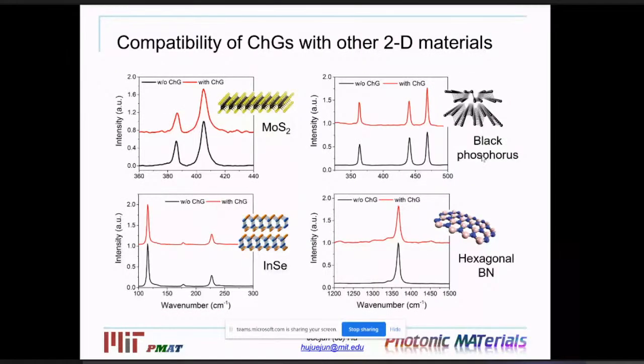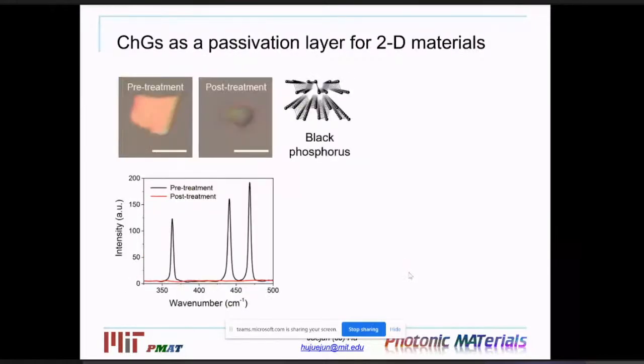And this characteristic applies not only to graphene, it also applies to any other kind of 2D material we have tried in the process. We tested different types of 2D materials ranging from transition metal dichalcogenides to black phosphorus to III-VI compounds as well as hexagonal boron nitride. In all cases, the material property of the 2D crystals is not compromised by the deposition of the chalcogenide. And in fact, they not only preserve the unique attributes of the underlying 2D materials, they can even serve as a protection layer to prevent chemical degradation of some of the less stable 2D materials.